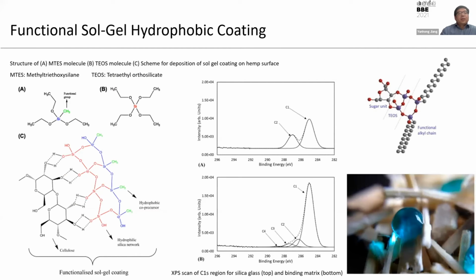So the project we developed uses functional sol-gel hydrophobic coatings. The MTES hydrophobic functional group can be added into the TEOS solutions. Then the functional alkyl chain can be bound to the sugar unit through the hydrophilic silica network. The modified functional sol-gel can change the surface of the hemp shiv from hydrophilic to hydrophobic by dip coating, as shown in the photos. The XPS data show the different bonding energy on the surface before and after modifications.